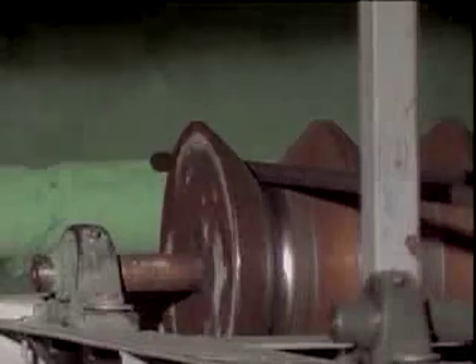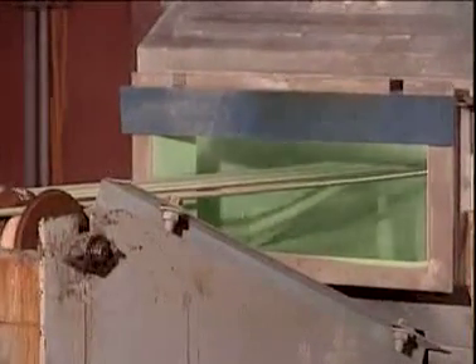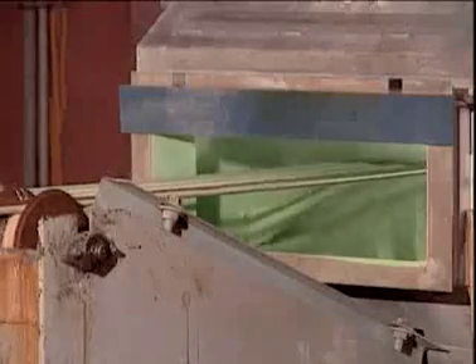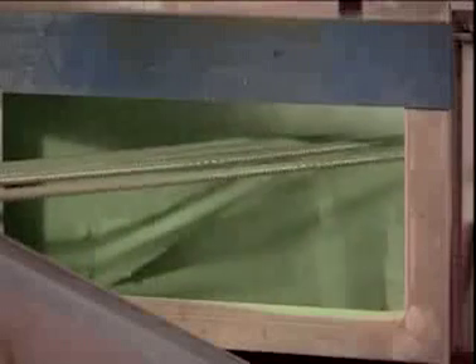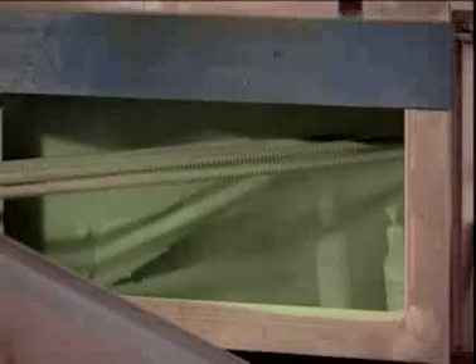Bars immediately pass through a powder spray booth where spray nozzles emit a dry epoxy powder. The spray guns impart an electrostatic charge to the powder particles. Charged powder particles are drawn to the grounded steel, resulting in complete and even coating. As the dry powder hits the hot steel, it melts and flows into the peaks and valleys on the surface of the steel, covering and conforming to the bars.